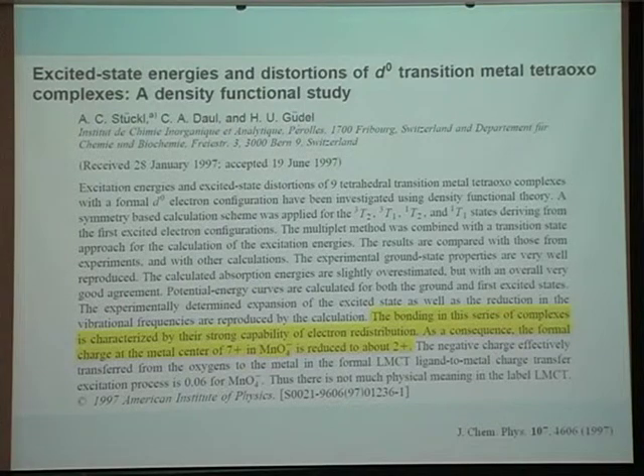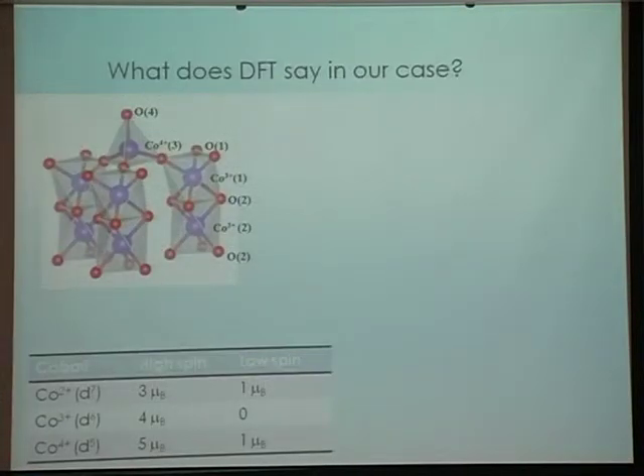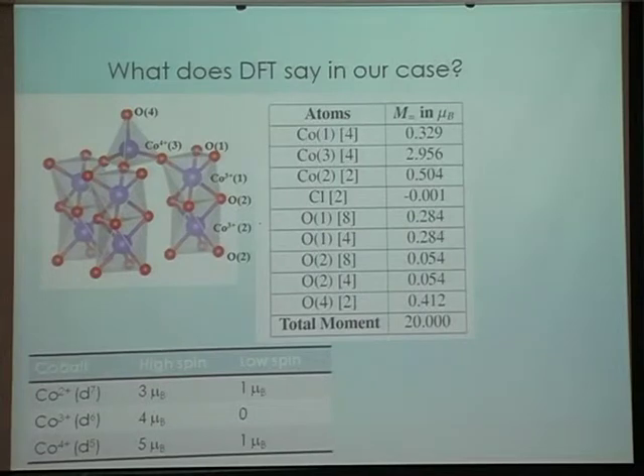Now the question that we ask: in our system that I showed you, we have cobalt in octahedral coordination as well as in tetrahedral coordination. And we did find that these lengths are much smaller than these lengths, not as different as manganese-oxygen, but still quite different. Whether something of that sort is actually happening or not, then Professor Tanushree Saha Dasgupta's group did some DFT calculations and gave us this number.